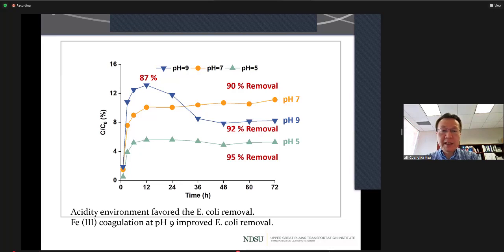And also, in order to confirm the pH impact from the batch study, we also compared the pH impact on the E. coli adsorption efficiency. We did observe that the acidic environment favored E. coli removal. So at pH 5, we were able to achieve 95% removal. And at pH 7, the removal efficiency reduced to 90%. And we observed some interesting results at pH 9. If you recall, during the batch study, pH 9 had the lowest removal efficiency. We did observe the lowest removal efficiency at the early stage of the column operation at 87%. However, as we continued to increase the operating time, the removal efficiency gradually increased to 92%.